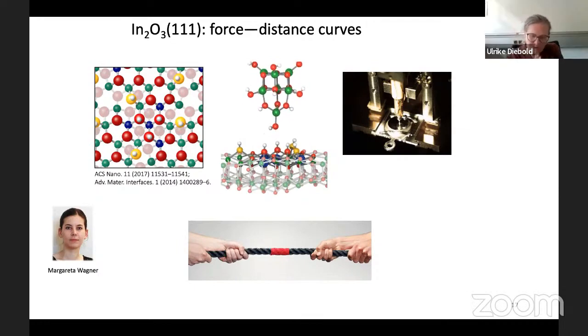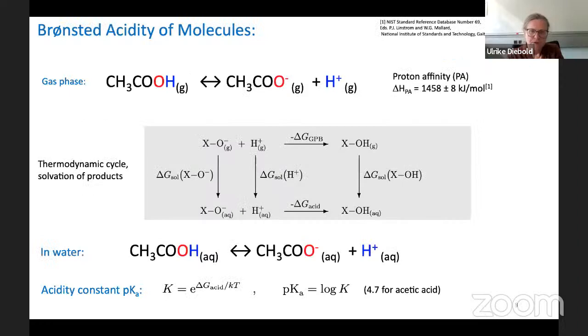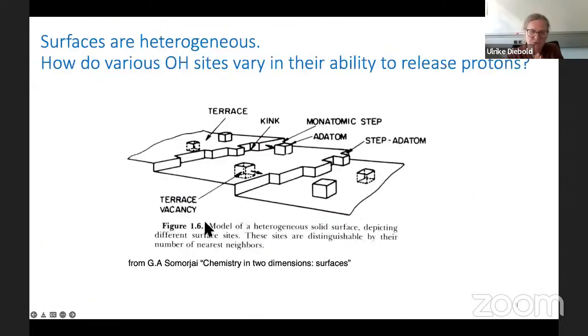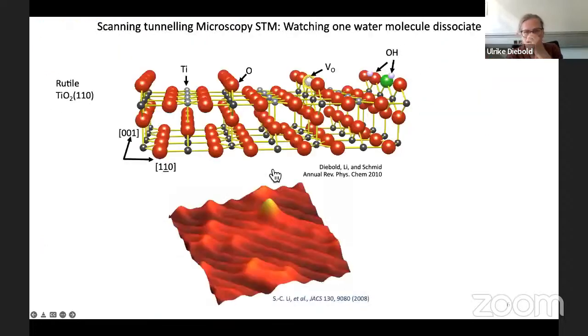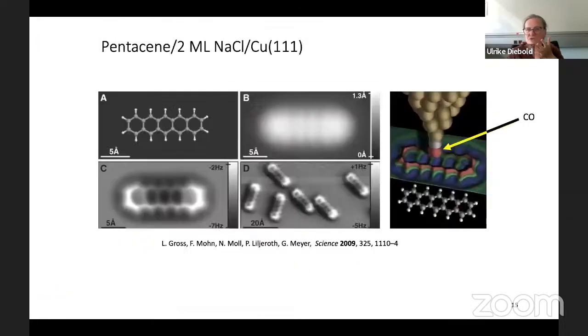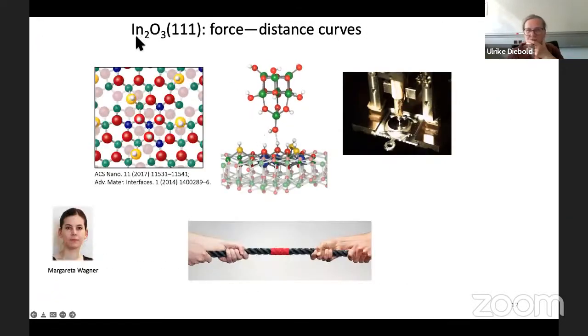If you look at this one here, where people have done these calculations, and I've shown you the same on the TiO2 STM, this is maybe easier. This is the surface, and here would be the bulk volume that we've just cut off. These oxygen atoms in the bulk have 3 neighbors, and they have also 3 neighbors here at the surface, but these oxygen atoms have only 2 neighbors because one is missing. So these oxygen atoms are clearly quite different from those. And in the particular case of the indium oxide that we use as our test bed, it just so turns out that this indium oxide has a bixbyite structure.